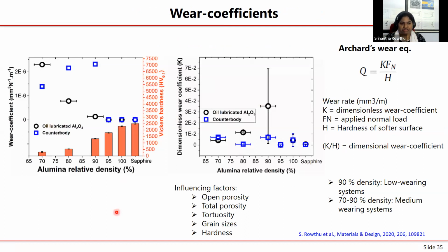Okay, now that we have characterized the friction coefficients, definitely we can also get rid of this. Now that we have finished characterizing the friction coefficient, we can also characterize the wear coefficients. So wear coefficients are, one is the so-called dimensionless wear coefficient, another one is the dimensional wear coefficient. So if you look at Archard's wear equation, you have Q equal to K F by H, where Q is nothing but your wear rate, which is given in millimeter cube, that is the amount of volume of the material that is removed per meter of the sliding distance, K is your dimensionless wear coefficient that is plotted here, F is the applied normal load, and H is the hardness of the softer material.